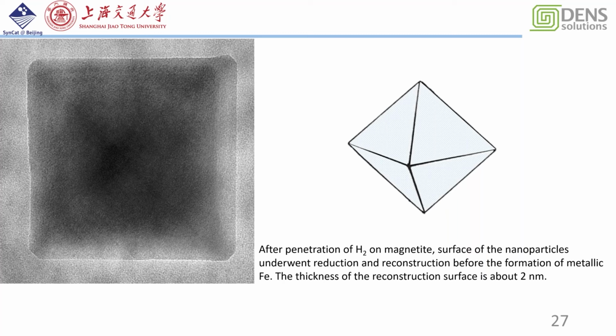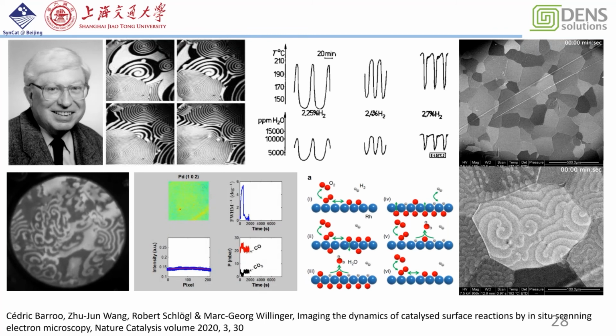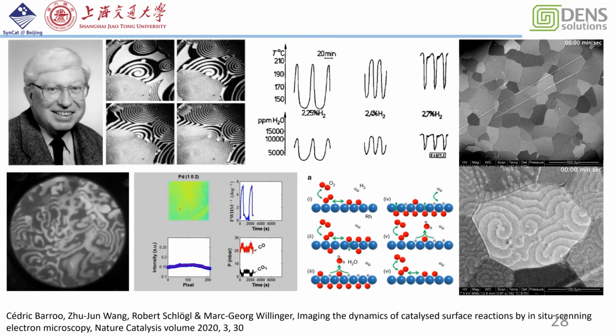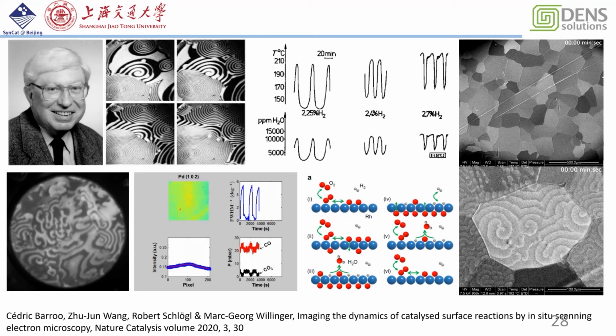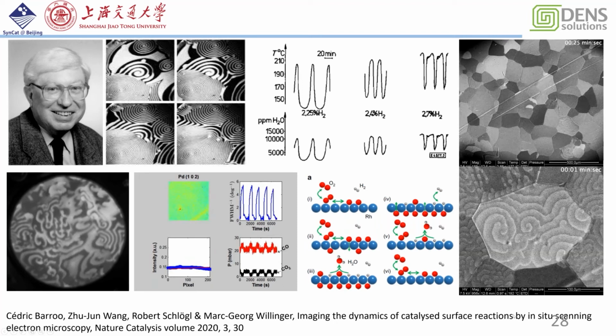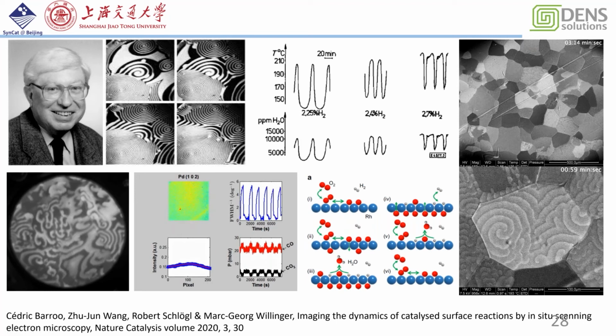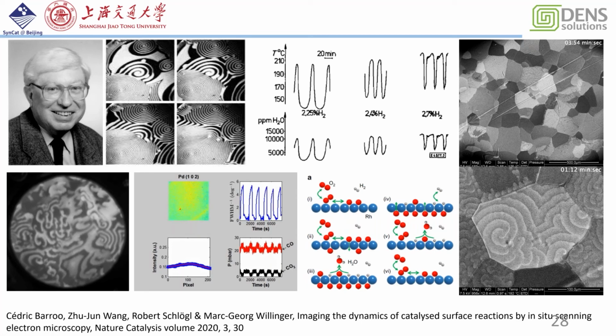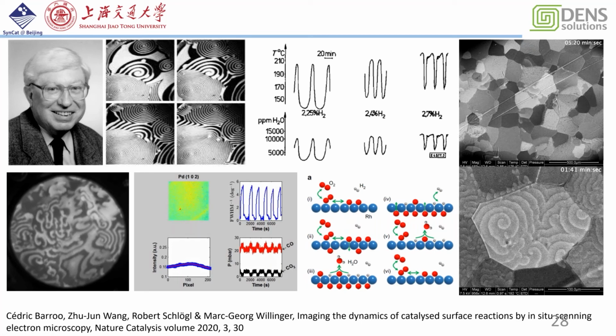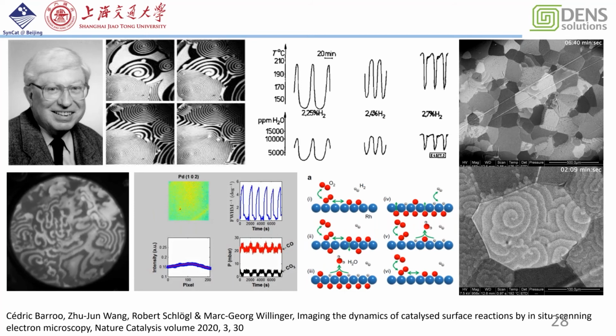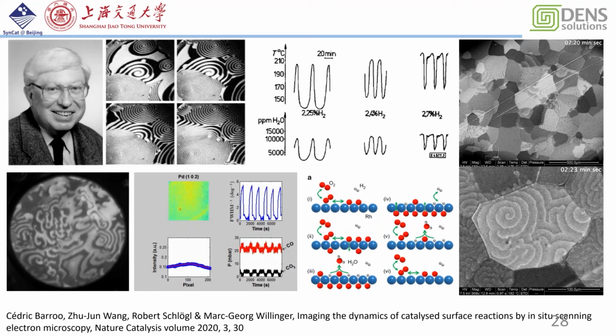It is quite interesting. If we correlate it to the reference, Professor Ertl discovered the spirals, the movement during the catalytic reaction. It is supposed that the hydrogen and the oxygen penetrated the subsurface and caused the reconstruction process. And recently, Dr. Zhu Junwang and Mark Willinger published a very beautiful paper to show this. They used SEM to visualize the spirals, the movement on the surface of the precious metal. And we can see this periodical change during the catalytic reaction. So this situation is quite similar to what we see in the reduction of the magnetite. But this is quite an irreversible process.